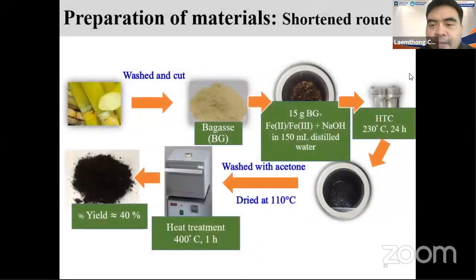Actually, what we did in this work, we call it the shortened route. We just have the raw bagasse. We wash the dust out of our precursor, and we simply put it together with iron 2 and iron 3. This is also the key to how to make the magnetic particle inside our carbon matrix. And we also put in the base, sodium hydroxide.